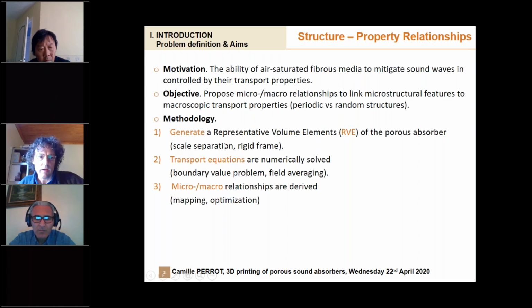Then you can solve transport equations, or basically boundary value problems, and by field averaging the solution fields properly, you come out with transport parameters or macroscopic parameters. Then you can link microstructural features you get at the lower scale from your representative volume element with the transport parameters you obtain from this numerical approach. It could also be an experimental approach, but this method provides you with a firm link, because there is a unique solution from the local geometry level to the macroscopic properties.